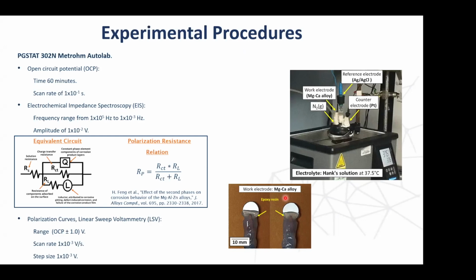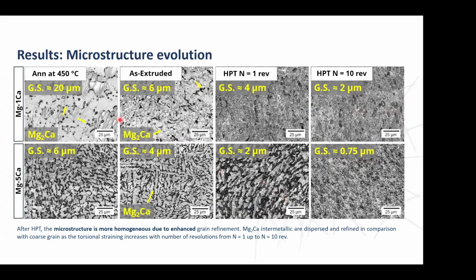microstructure to the biodegradation. So usually magnesium calcium will have a magnesium matrix and second phase particles composed of magnesium two calcium. And then we can see here, we started from an annealed microstructure, and we were given some extruded bars from the Magnesium Research Center in Japan. And then with these extruded bars, we cut some discs, and then we processed them by HPT.